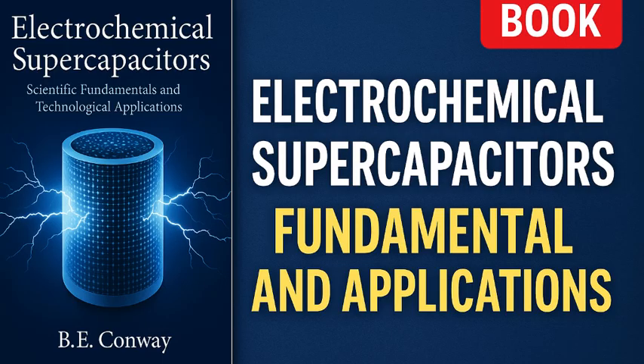For example, acetonitrile has a moderate dielectric constant and low viscosity, making it a popular choice that yields high power performance. Propylene carbonate has a higher dielectric constant but is more viscous. Sometimes mixtures of solvents are used to get the best of both, a tactic to reduce viscosity while still minimizing ion pairing. Temperature also plays a role.